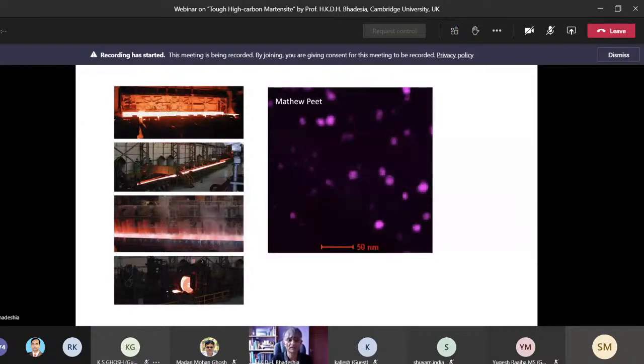And the process is wonderful. You can mass produce as much material as you want by hot rolling and by cooling, and then you end up with a coil which is then sliced up. These are high resolution images. The scale is 50 nanometers. High resolution images to show you the very small vanadium carbide particles which help this process.